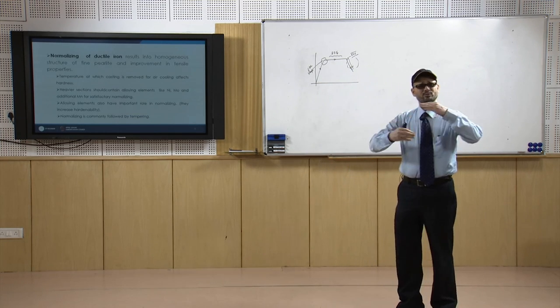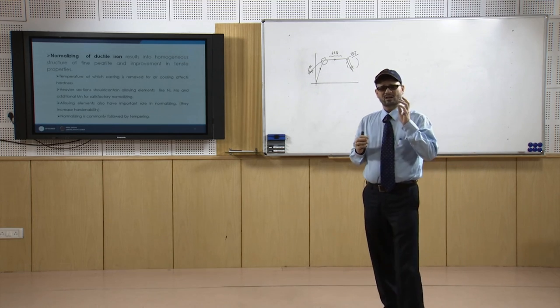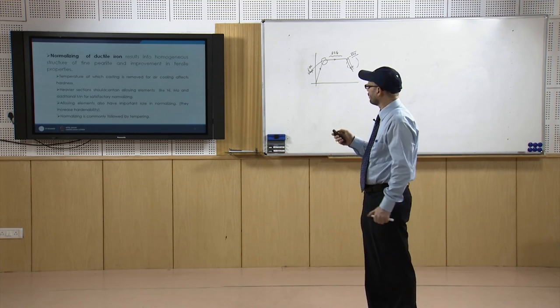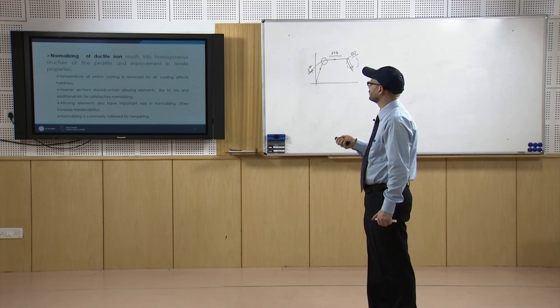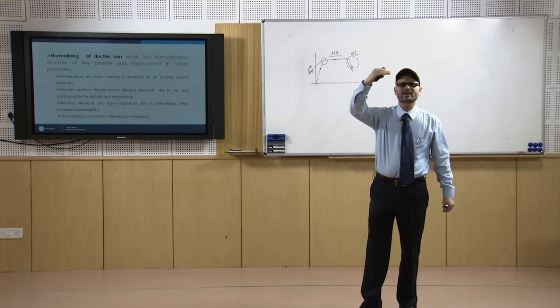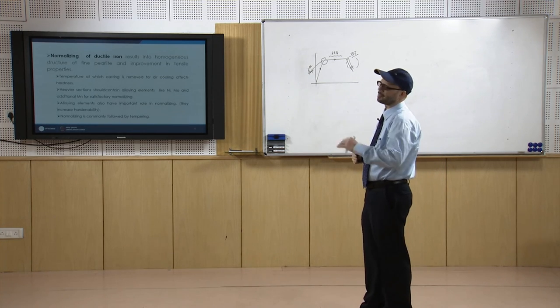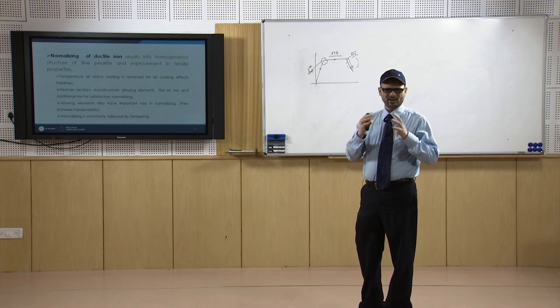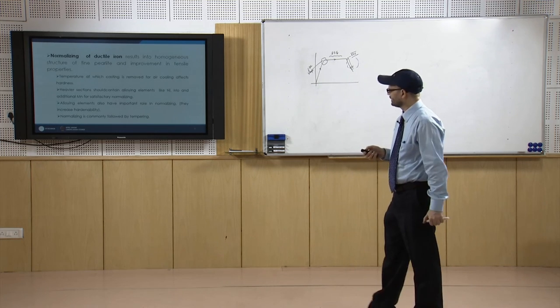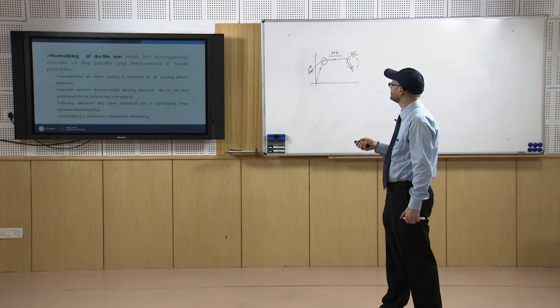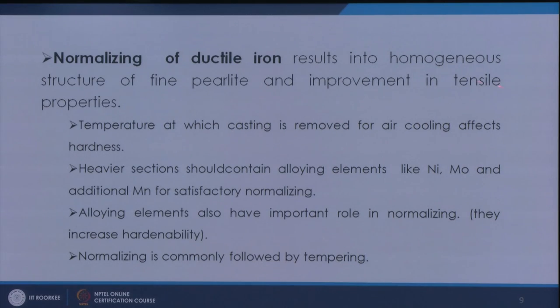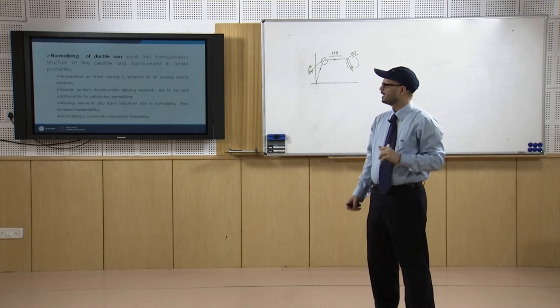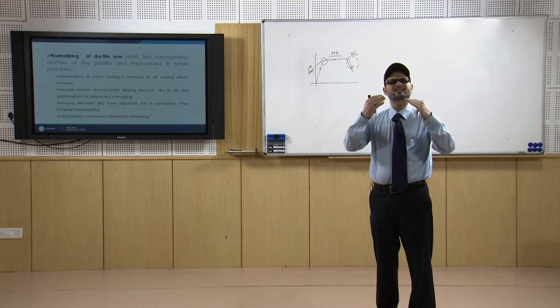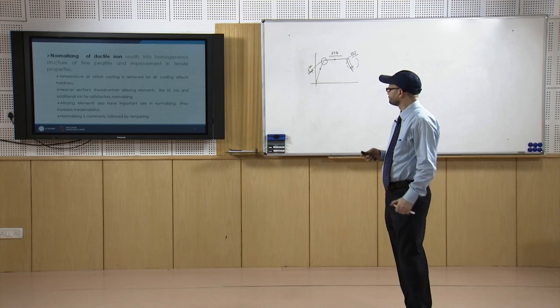Now, if you discuss the heat treatment of ductile iron, you can go for normalizing of the ductile iron. Normalizing means you are going into the range of 900 to 950 degree centigrade and holding for some time, and then you are cooling in normal atmospheric air. That results in a homogeneous structure of fine pearlite and improvement in tensile properties. So if you are going for normalizing and not cooling very slowly, instead of ferrite you get the fine pearlitic matrix.